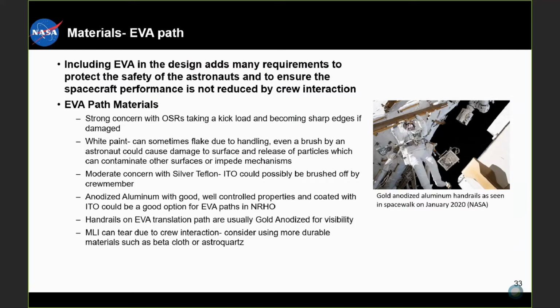Next, we have white paint. This also has concerns around it because it can sometimes flake due to handling. Even a brush by an astronaut could cause damage to the surface, which could ultimately contaminate other surfaces or impede mechanisms. With the silver Teflon ITO, there's a moderate concern that it also could be brushed off by the crew member. With anodized aluminum, this is a good material and it has well-controlled properties. And when coated with ITO, it could be a good option for the EVA paths in NRHO.